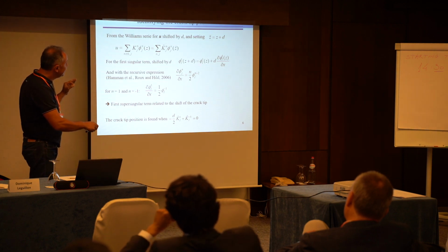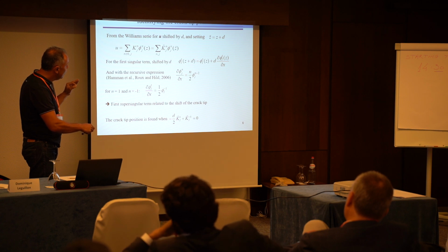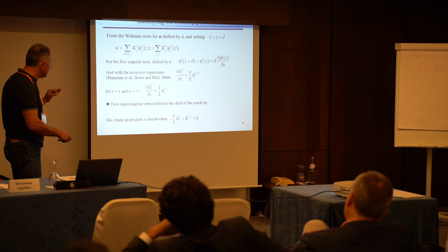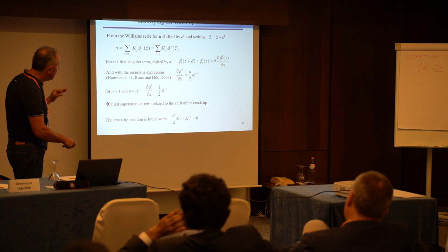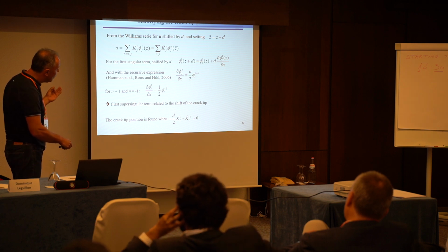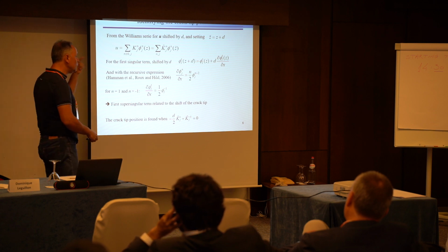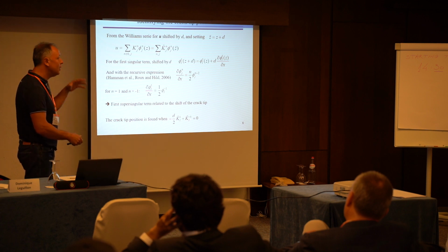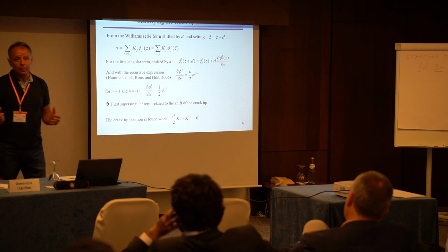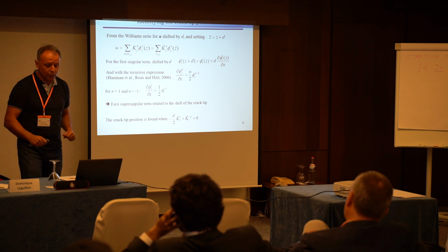So there is a recurrent expression here that allows you to detect the position of the tip by looking at the K1, the standard K1 term, and what Hild and Roux call the first super-singular term, which in Dominique's language is the dual mode.